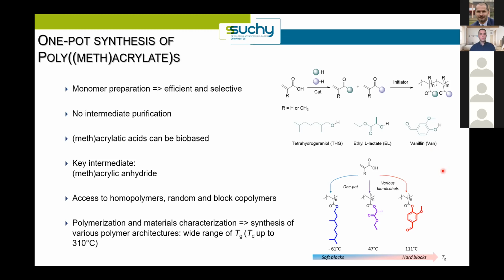Starting from these monomers, different types of polymers can be obtained, such as homopolymers, random copolymers, or block copolymers. And the alcohols used give plastics their main thermal or mechanical properties, such as flexibility or hardness. For instance, the homopolymer of ethyl lactate displays a Tg at 47 degrees, while the homopolymer of vanillin methacrylate has a much higher glass transition temperature.